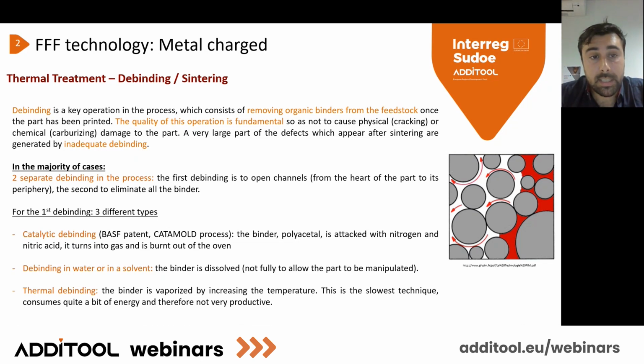And then for the first debinding, the last type is a complete thermal debinding. In thermal debinding, the binder is vaporized by increasing the temperature very softly to avoid cracking and damage on the part or deformation. So it's important to note that this is the slowest technique and consumes quite a bit of energy, and therefore it's not very productive, okay? And it consumes a lot of gas also.